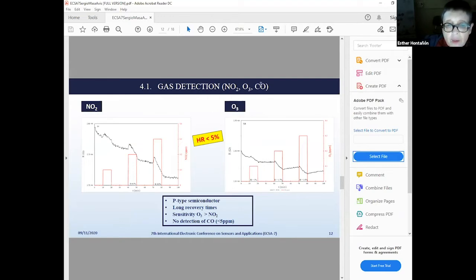First, I have to say that we tried to perform measurements with carbon monoxide too, but with this particular sensor I mentioned before, it was not possible. It was not able to detect CO up to 5 ppm, which is a concentration range relevant for air quality applications. This can be a good point or a bad point, depending on how you look at the result, because it's not able to detect CO. We can say it's more selective to oxidizing gases. So the interference with CO and maybe other non-oxidizing gases is less, or there is no interference at all.